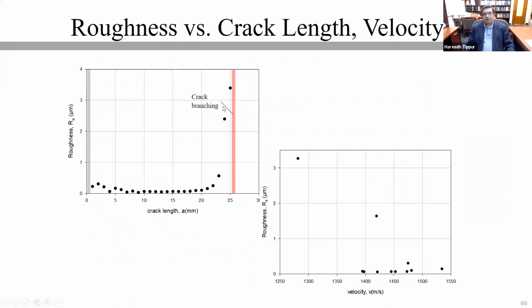Roughness was plotted based on the existing polymer literature. I again plotted roughness as a function of crack length in this case, and then crack velocity. When you look at the fracture surface roughness as a function of crack length, you see that in the mirror region, these are the low values here. This is where the crack initiated.